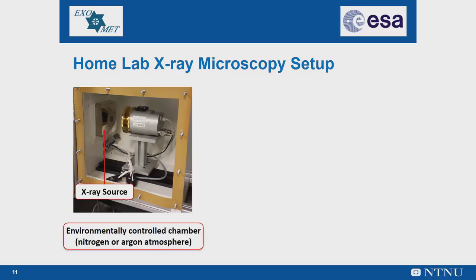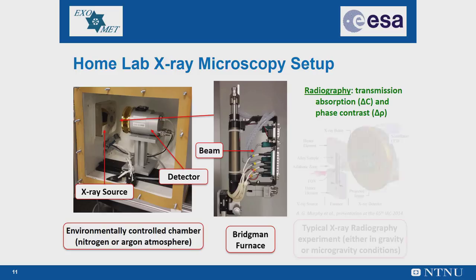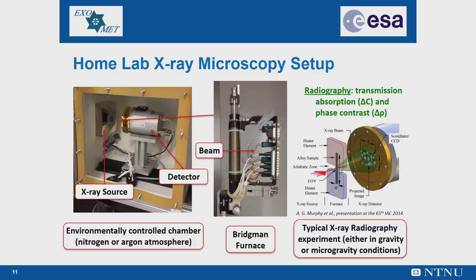The detector comprises a digital camera with a CCD sensor adapted for X-ray usage. A scintillator plate placed in front of the optical fiber converts X-ray radiation to visible spectrum light. The gradient furnace is of Bridgman type, with two identical heaters for the hot and cold zones; the heaters are independently regulated via software. Two thermocouples in each heater measure the temperature close to the crucible and serve as input for temperature regulation. The gap between heaters has a hole for X-ray radiation transmission. In a typical solidification experiment, the sample is placed in the furnace and melted, then solidified by operating on different parameters such as the cooling rate or pulling speed.